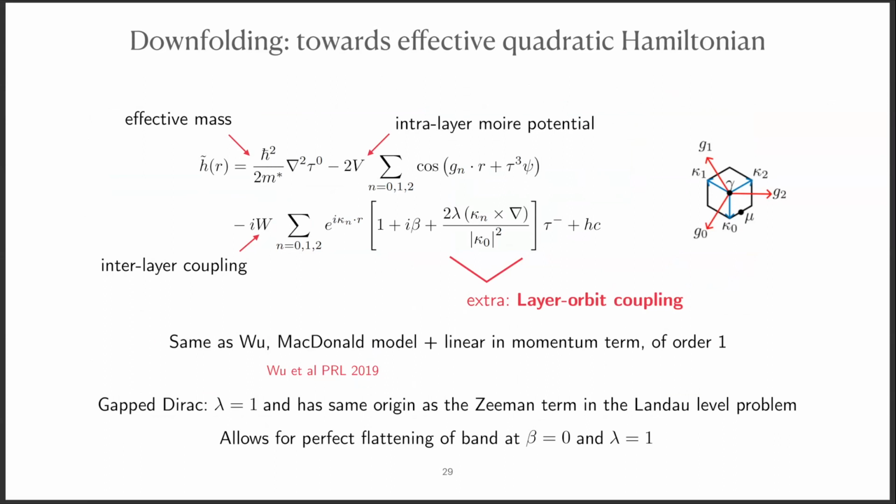What I am saying is that you absolutely need this term to make it perfectly ideal, to make it perfectly flat. This is necessary, because you cannot put a quadratic band under any potential. You cannot make a band which is perfectly flat. That's a theorem. So you need this term in order to make it perfectly flat. Now, it turns out that you can engineer the other terms independently to make something that is quite close to flat. So you just have many parameters in the model, basically.